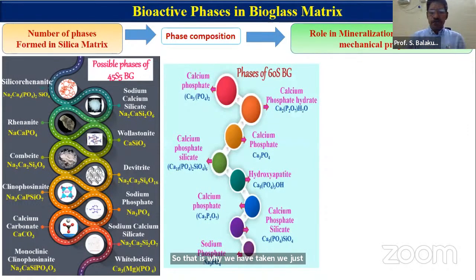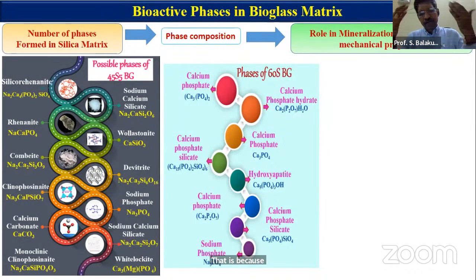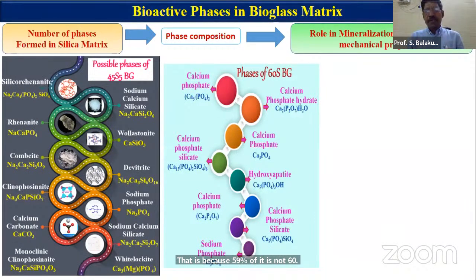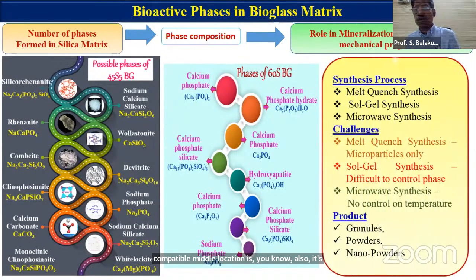We have introduced a new composition that we developed in the lab without sodium. We call it 59% silica. It is not 60, actually it is 59% of silica. And we systematically developed a material; this group of materials is mechanically highly stable and biocompatible. Mineralization is still comparable. This material can be used. So we also studied this and systematically evaluated the challenges.